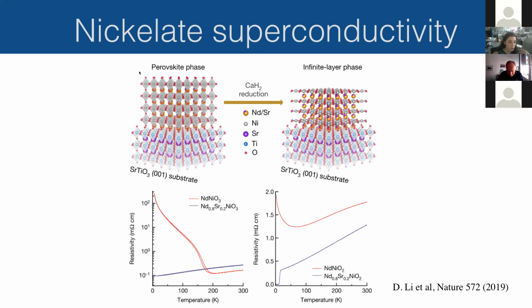Happily for those of us who work with perovskite nickelates, we are still relevant in this study because they start from the perovskite phase as a thin film, and then they do topotactic reduction. So it's something where you use a powder which sucks out the oxygens that are sitting on the apical sites, preferentially, leaving behind the infinite layer phase. So when you really optimize this kind of reduction process, what you end up with is some beautiful crystal like this, and then you dope it, and then it becomes superconducting.